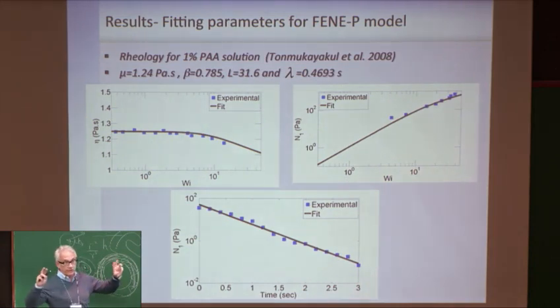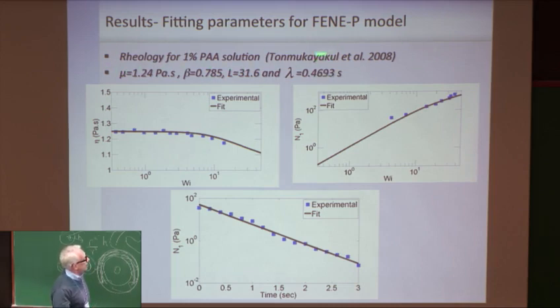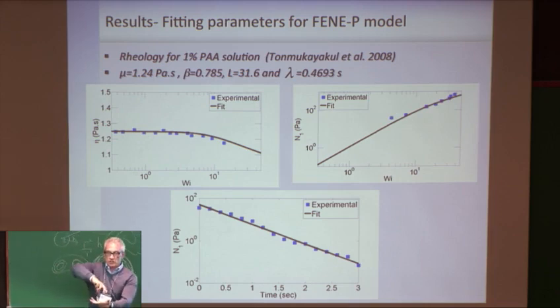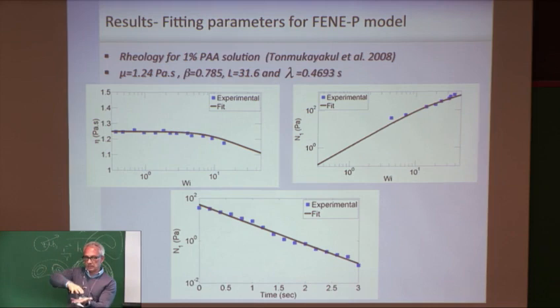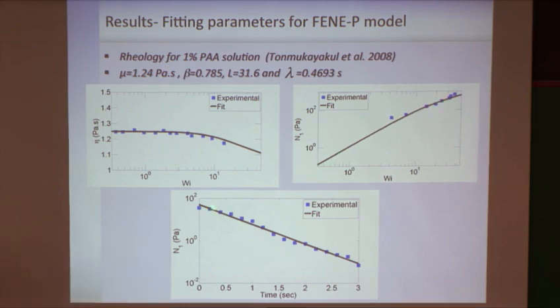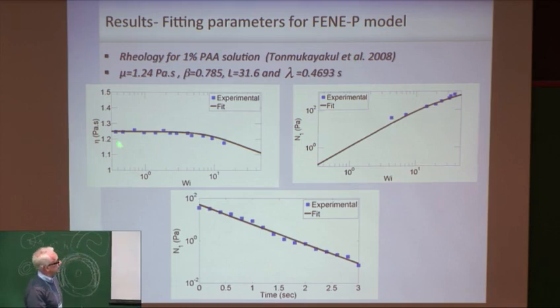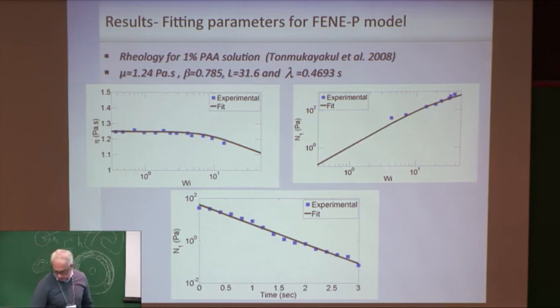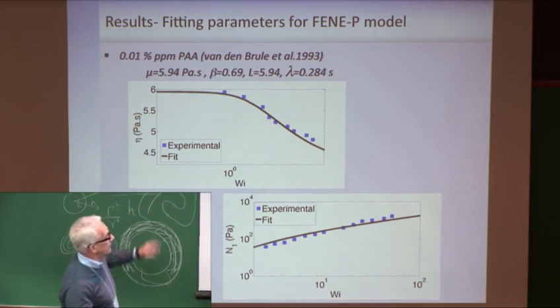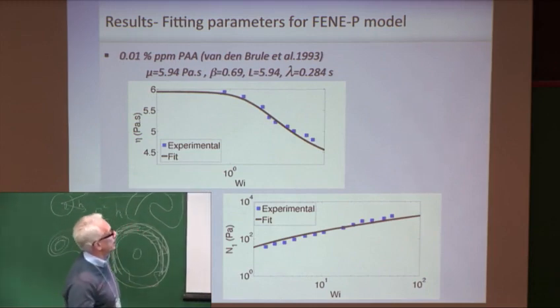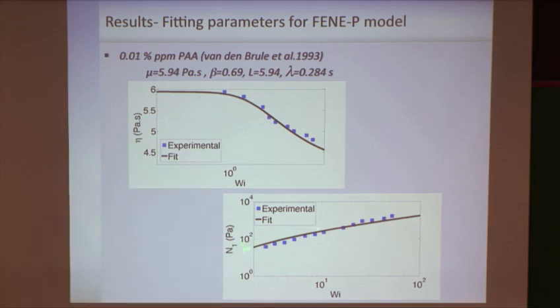Let's go to the parameters and the interesting fluids. These are all going to be good fluids, good fracking fluids. This is the fluid from Halliburton. It's a polyacrylamide solution at 1%. This is the shear viscosity that you measure in a rheometer. These are the so-called normal stresses. When you spin one of these fluids, the plates are pushed apart naturally because of the elasticity. You can fit that experiment as well. This is an experiment where you shut off the rheometer and you measure the relaxation of the force, the normal thrust force. You get that as well. The point is that the Fene-P model, in this case, with these parameters, can match the shear rheology of this fluid. This is the fluid that originally van den Brule in the early 90s looked at. It's a 0.01% polyacrylamide solution. We can match the shear viscosity and the steady normal stress for this fluid with this set of parameters for the Fene-P model.